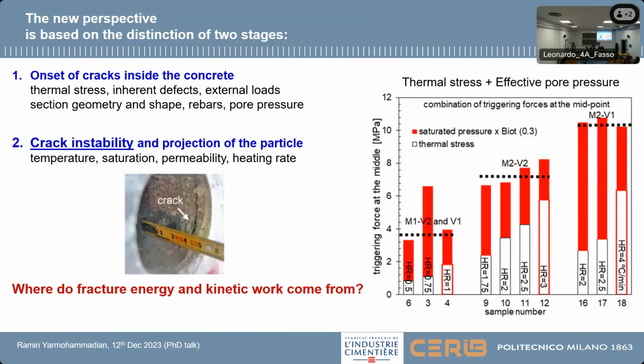So today we want to explain it in a different way. In our new perspective, the spalling consists of two stages. The first stage is cracking, and the second stage, which follows the first one, is instability of the crack. In my thesis, I started to explain a bit about the first stage, which is the crack generation. For example, I used one of the results from another PhD student to see how the combination of thermal stress and effective pore pressure can generate this spalling, in ultra-high performance concrete, in a cylindrical specimen.